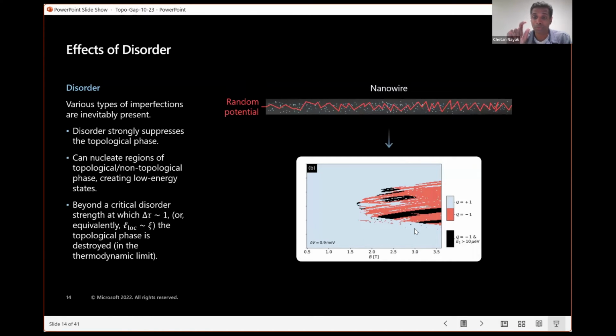And in fact, if you require not only that it's a topological phase, but also a gap larger than some minimum value, which is 10 microelectronvolts, then you can see the topological phase breaks into even smaller regions. So disorder changes the look of the phase diagram significantly, breaks a large parabolic topological region into these small fragments. Okay, and ultimately, when the disorder gets too strong, you don't even have those, and the topological phase is